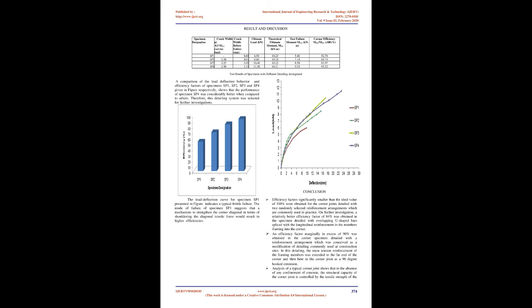Baty dial gauges with magnetic base were used to measure the deflections in the vertical framing members at the points of load application. The least count and stroke of these dial gauges was 0.01 mm and 25 mm respectively. Demec strain gauges of 100 mm gauge length were used for measuring concrete surface strains at selected locations along the corner diagonal of the specimen. The least count of the gauge was 0.0001 inches.